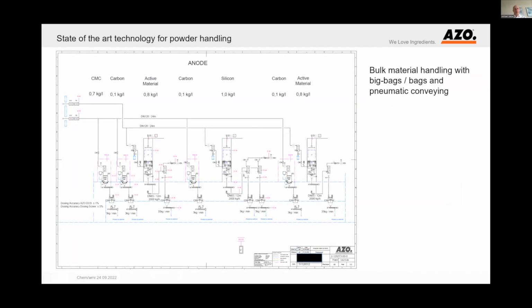Okay, so now I'd like to show you a diagram with a typical arrangement for a gigafactory, let's say 6 or 10 gigawatt hours. So this diagram shows a combination of a pneumatic system and a gravimetric feeding system. So the materials, the smaller amounts like the binders and conductive materials, are delivered in bags. Then we have these bag feeding stations here, and they are feeding the material to loss-in-weight feeders. If it's an AZO product, it's a so-called AZO-DOS system.